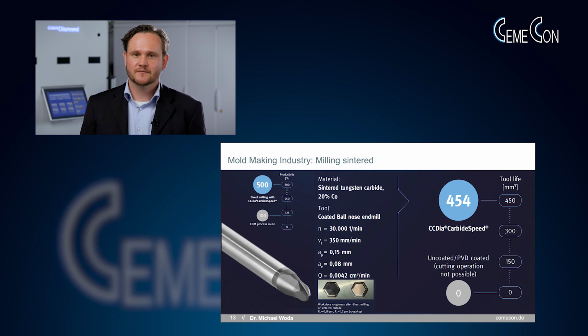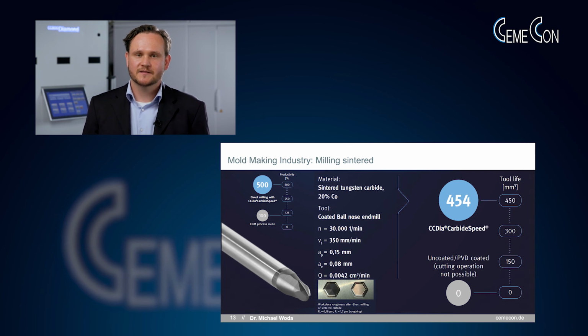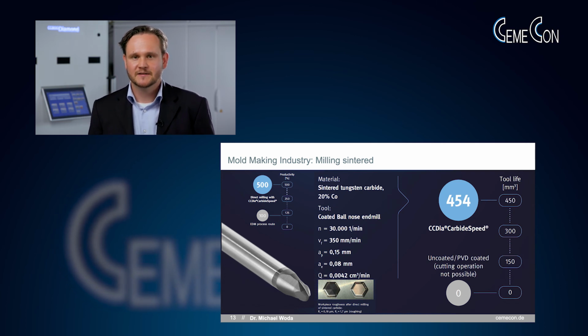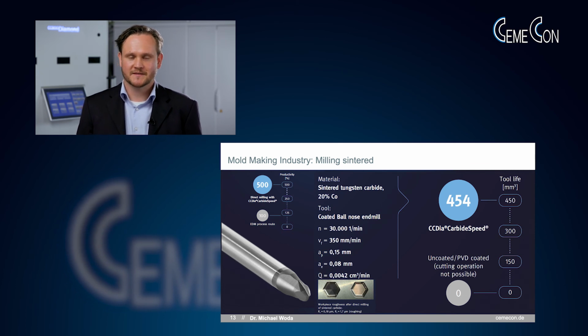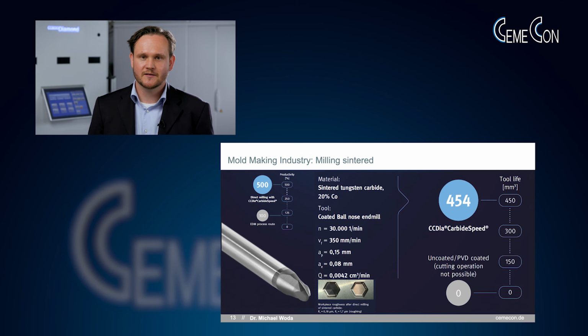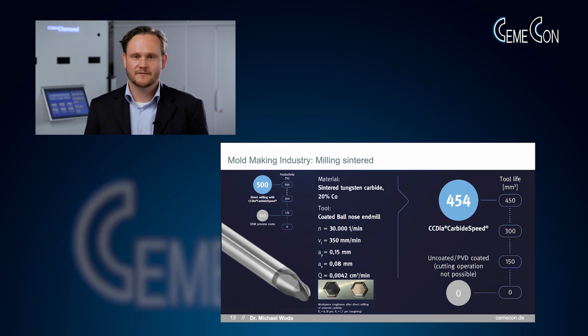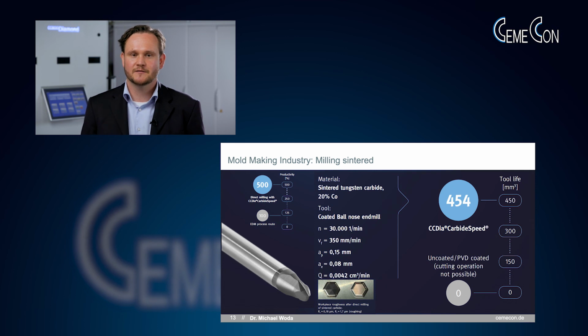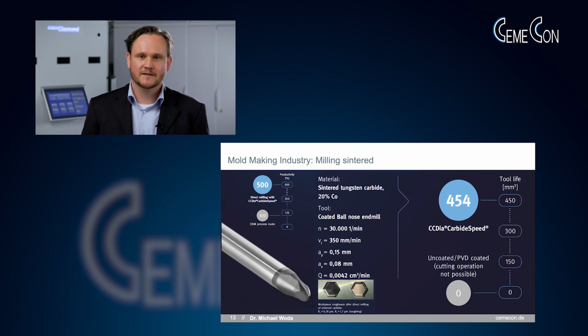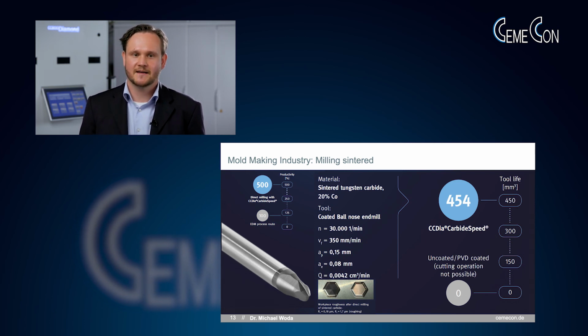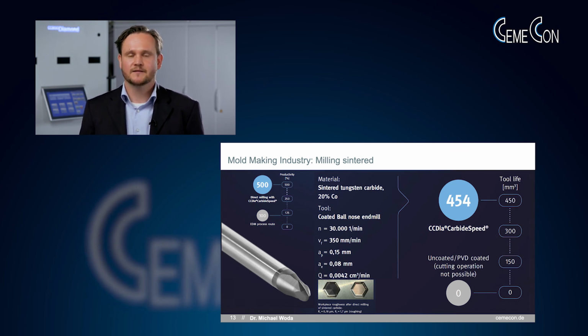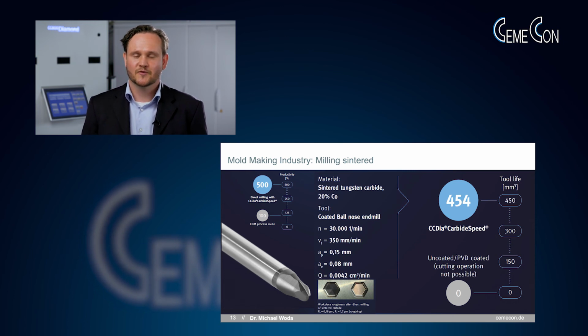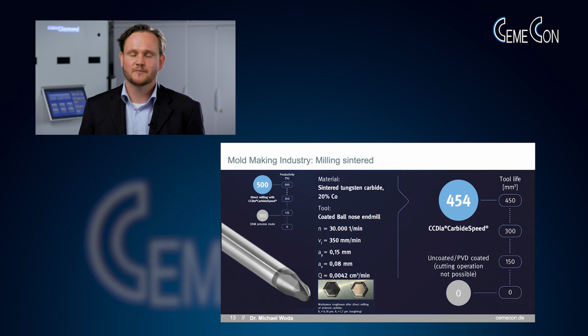In this slide, some recent results of a coating called carbide speed are shown. We are here milling a 20% cobalt carbide with a ball nose end mill at the listed cutting parameters. So we are using very high spindle speeds here, and we are able to remove almost 500 cubic millimeters of sintered carbide material with the help of the diamond coating. Whereas the uncoated or PVD coating is not able to perform this task at all. So finally, the mold maker has the opportunity to gain an improvement of about 500% on productivity in terms of saved process time.